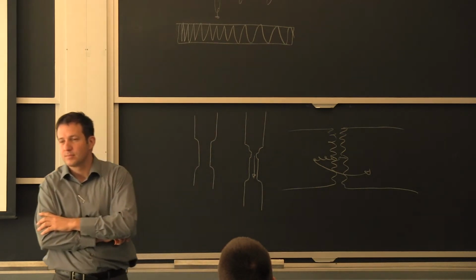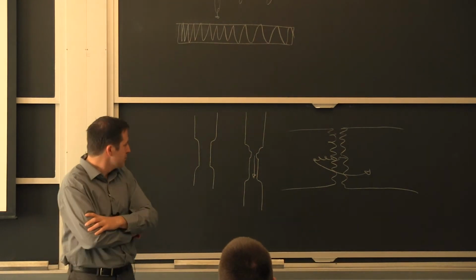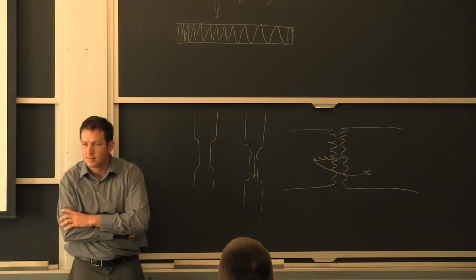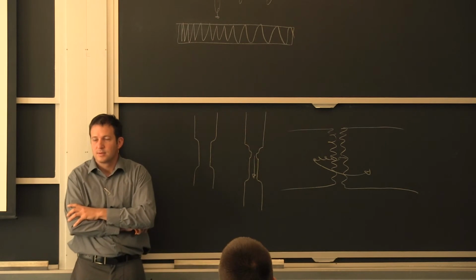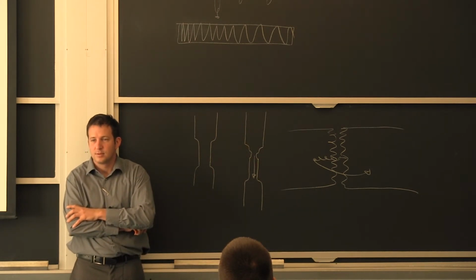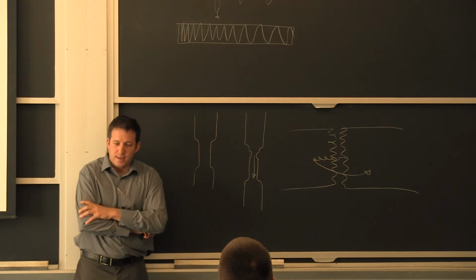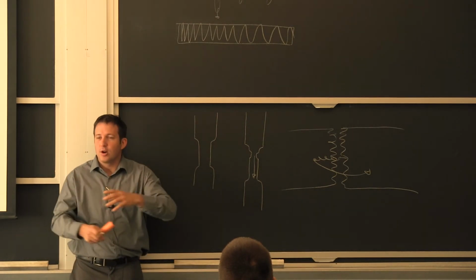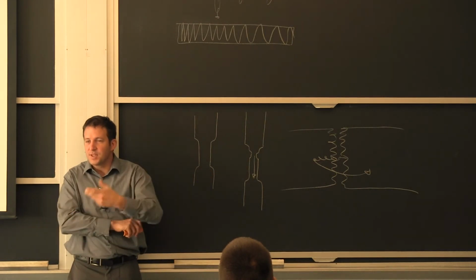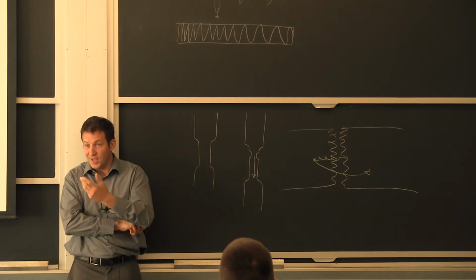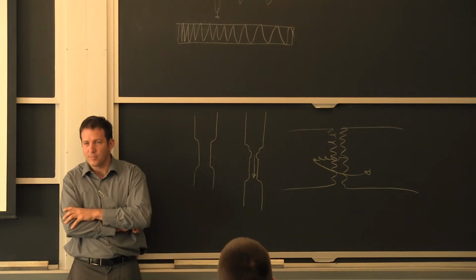And then when you want those chains to interpenetrate, when you're doing the... Yes. You want the relaxation time of the reptation tube, not the polymer inside the tube, right? Yeah, so that's right. You need a large distance movement, so it's a viscous flow, and that's why you need heat to make it happen. Very good.